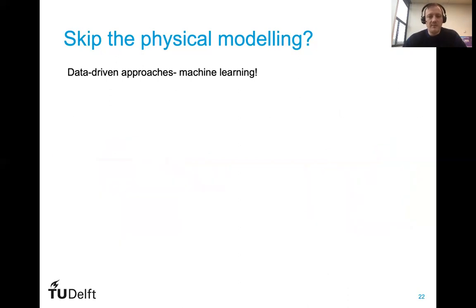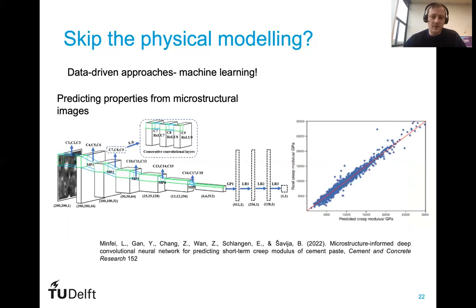Another approach that we recently attempted was to predict properties of materials from microstructural images. So we have performed X-ray CT of cement paste, and based on X-ray CT data, we created a convolutional neural network, which is able to predict the creep modulus only from the microstructure. Of course, for this, we used the model that I presented before for creep calculations. So we trained our network based on the modeling results, and then we tested whether we can use this trained network to predict the creep modulus, and this worked very well. So you can see more details in this recent publication.